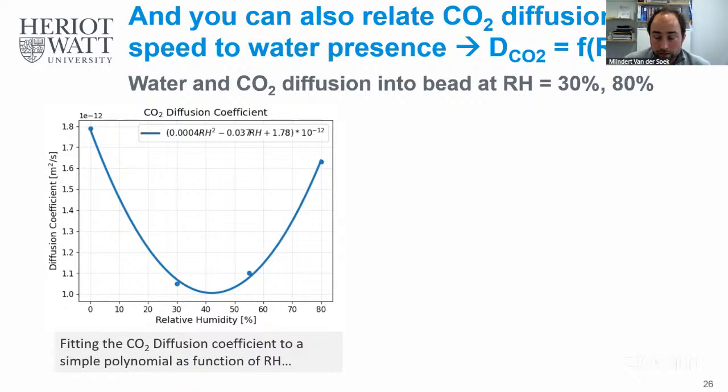Yes, absolutely. Both CO2 and water are solvents for amine functionalized polymer resins. So not necessarily for every polymer resin, but for the amine functionalized ones for sure. But the nature of the adsorption is very different, because water condenses at room conditions, at least if the relative humidity approaches 100%, and CO2 doesn't start condensing until close to the critical point. So the amount of swelling is different, but they both have the ability to solvate polymer resins.